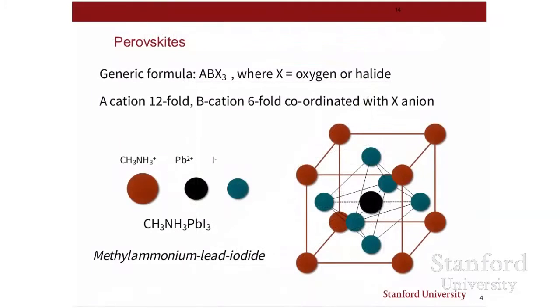Okay, now let me tell you about the perovskites themselves. Perovskites are essentially a salt, and you can dissolve them in a polar solvent. And when you do, you really don't have perovskite in your vial of solution. You have ions in there. But then when you cast it or print it and form a thin film, the solvent will evaporate away. And as it does, the salt will form, and it'll be solid. And you'll get a crystal structure like you can see on the right side of the slide. The word perovskite really means just that crystal structure. It means the atoms are arranged in that way.